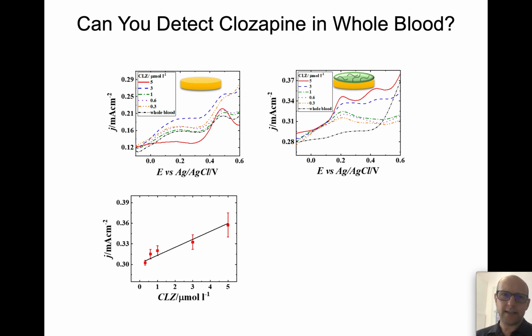So the big question is, can we use this sensor to measure clozapine directly in whole blood? And for that we tested the electrochemical signatures. We took whole blood from volunteers, and within 5 minutes we spiked it with clozapine and measured the signal. On the left-hand side measured with a bare electrode, and on the right-hand side with the chitosan-carbon nanotube. And we built the calibration curve by looking at the signals at 0.2 volts, which in the previous slide I showed you was the signal from the clozapine with the chitosan-carbon nanotube.